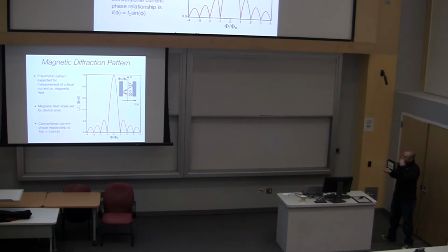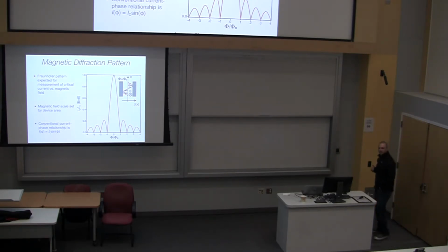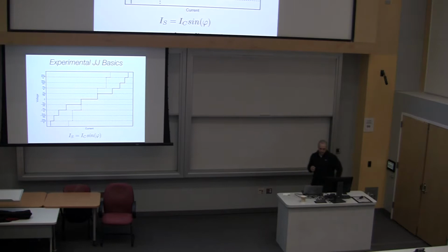So this is one thing we always look for when making our junctions, because one of the failure modes is you might have a junction but then a small little superconductor that didn't lift off is kind of shorting your junction out. It'll have a small supercurrent, so it looks like it's going through the junction, but it's really not the Josephson junction we want. But if we can measure some Fraunhofer-like pattern, we know that there's a roughly uniform distribution of supercurrent, no shorts in the device. And we're actually going to use this pattern too to investigate some of the properties of the material.